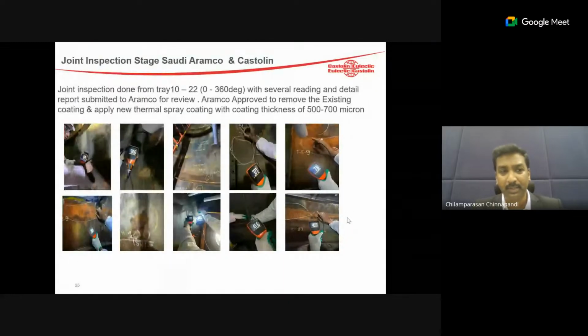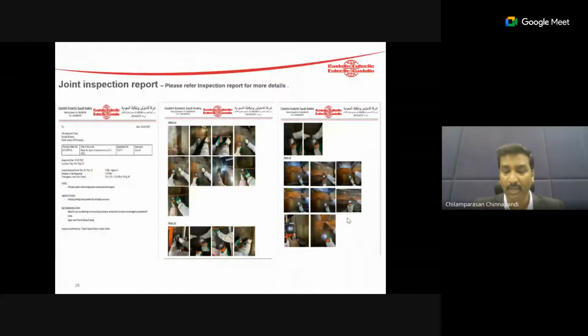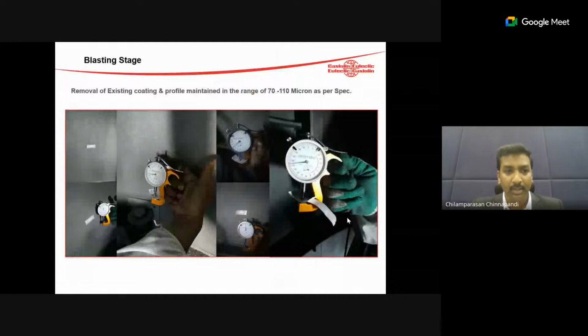So this was the condition of the component when opened, where the existing coating had been damaged. We did the inspections, and we had a joint inspection with the customer. The existing coating was removed and the profile maintained, because we need to completely remove the existing coating, which had pitting, corrosion and damage. So we need to remove the complete coating and do the blasting to avoid any moisture contents, and the profile has to be maintained before spray.